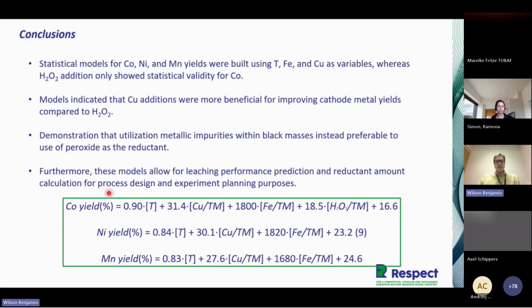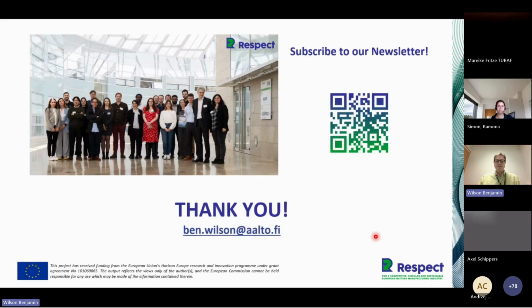So we're able to look at these models as a way of performing leaching performance predictions. This is based on NMC 111, but as you can see from the equations we now have based on the models, it is possible to take an NMC, maybe 532, for example, and then calculate, based on the different temperatures that would be appropriate for leaching, what kind of yields would be applicable from this new material.